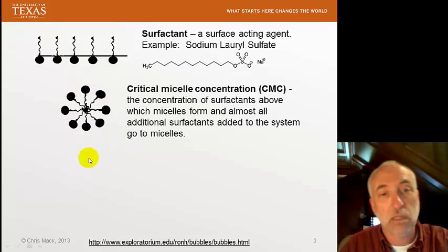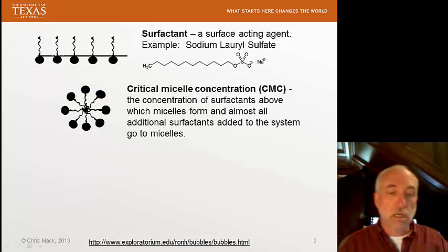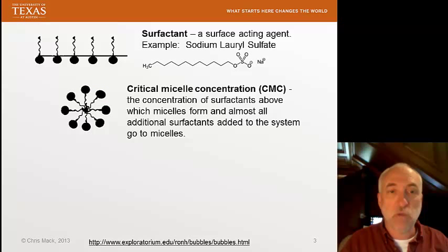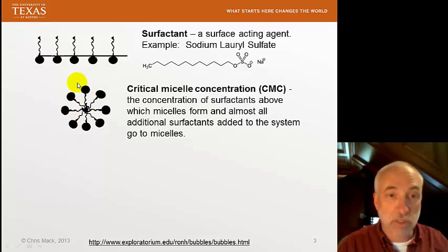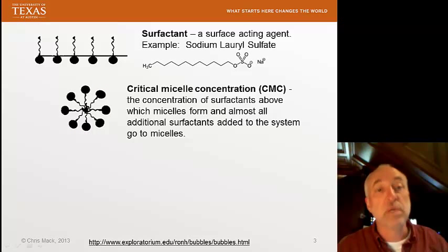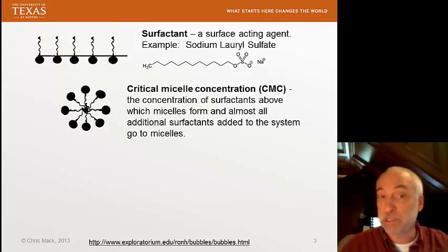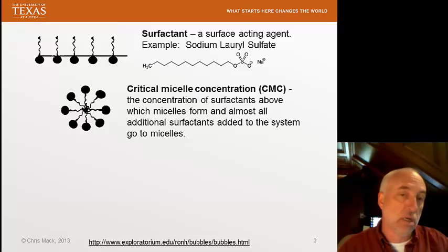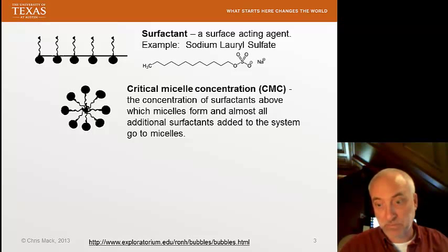This is a micelle. A micelle is a construction of these surfactants where there's a high enough concentration, called the critical micelle concentration, where the surfactants find each other, and all of the tails, the lipid ends of the surfactant, interact with each other, having an outside region that's all polar, and if the outside world is water, let's say, then this will be a more energetically favorable, a more stable configuration of the surfactants.